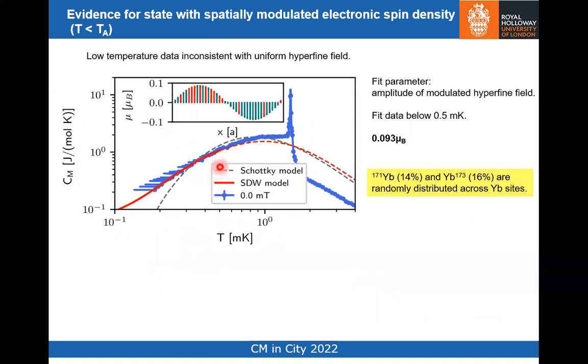So now if we just look at the data at extremely low temperatures, we can't explain that data in terms of a uniform hyperfine field experienced by the nuclei, because they would give a too rapid roll-off in the heat capacity. What we have to do is posit a modulated hyperfine field, such as would arise from a spin density wave, as indicated here. So there's a modulated electronic moment. It's incommensurate with the lattice.